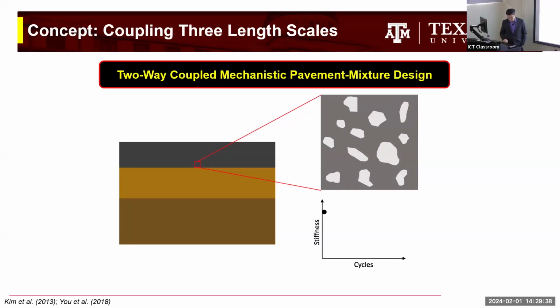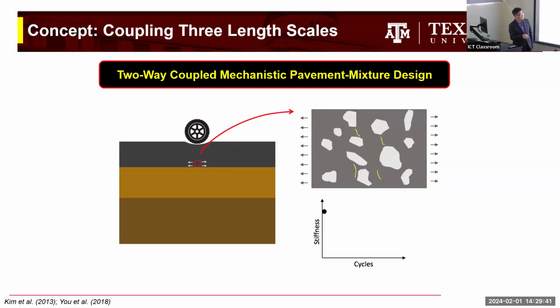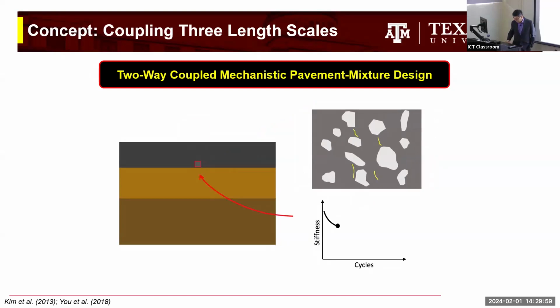And then I apply truck loads. Right there, because of tension, we may develop a little micro cracks. These micro cracks will make the location weaken, so your stiffness will be dropping. That reduced stiffness should be the property for the next time step. Realistically, your property will not be the same as before. It will be degraded because of damage, and that amount of degradation is different from here to there, right? Because of the loading condition and your boundary condition.